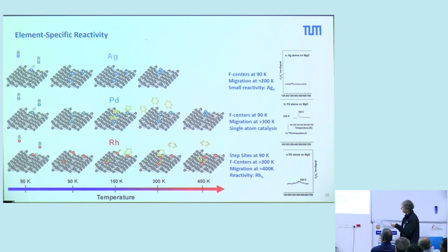On silver, this very tiny peak, it's certainly not from atoms. We produce clusters. On palladium, we have strong evidence that it is indeed these single atoms. On the rhodium, of course, at the temperature of 430 K, we produce clusters. That means this is the reactivity of clusters and not of single atoms.